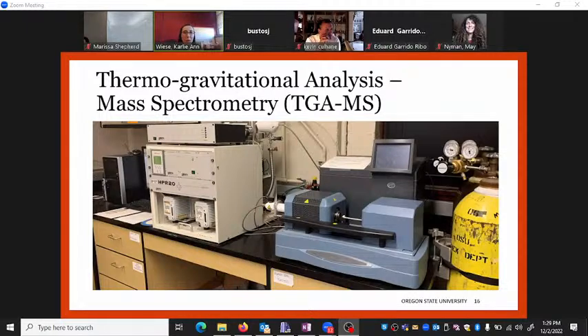Another thing I use is thermogravimetric analysis and mass spectrometry, so TGA mass spec. And this right here is the TGA. You place your sample in, it weighs your sample at the beginning and then heats your sample up to very high temperatures, like 800 or 900 degrees Celsius. And as it does that, your sample will decompose and release gases, and it records the weight loss. So you have the initial and final weight of the sample, and you know how much has been lost to gas. And then the mass spec will analyze all the gases that have been released, separate them, and tell you which different gases were released from your sample.